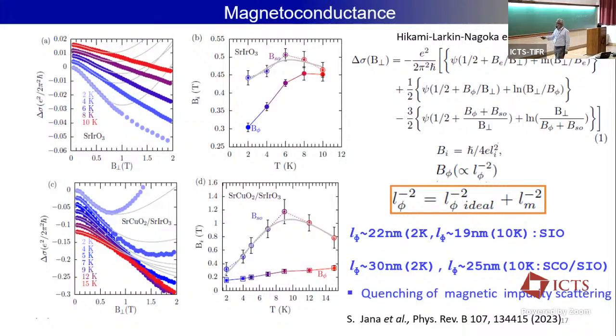From this B phi, you can calculate that L phi for the bare SrIrO3 is roughly 22 nanometers at 2 Kelvin. But in the case of the bilayer, when you put strontium iridate on top of an antiferromagnetic insulator, the L phi is increasing. That is the kind of scenario we see, where they were looking at the spin flip scattering time anomalously increasing.